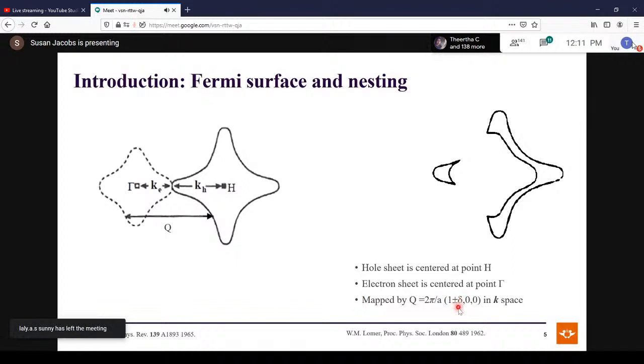Here, the delta is what we call the incommensurability parameter, and it arises due to the size mismatch between the electron sheet and the hole sheet. So in order to reduce delta, we have to dope with elements that are electron donors so as to increase the size of the electron sheet. Okay, so nesting leads to spin density wave formation. What happens is the electron sheet is translated onto the hole sheet, and as a result, there is Coulombic interaction between the electrons and holes, and parts of the Fermi surface are annihilated as a result of that.